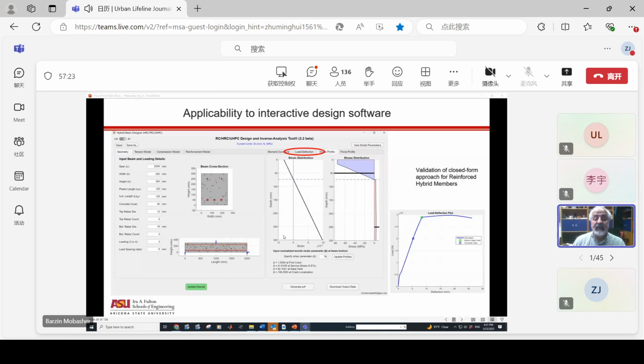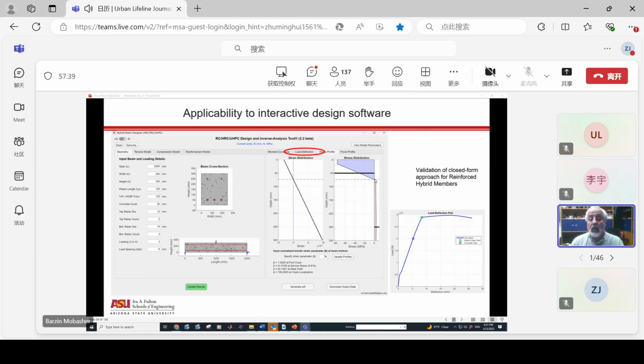Recently, we've worked on actually making them more user-friendly, where the parameters are input, and we can get the strain distribution and stress distribution. And if you look at this curve, you can see that it really doesn't matter what the shape of the curve is. We get all of this concrete, which is more than 70% of the depth of the material, carrying 2 megapascal. And 2 megapascal multiplied by this area far outweighs how much force your steel is carrying.